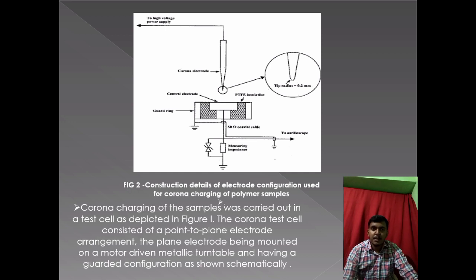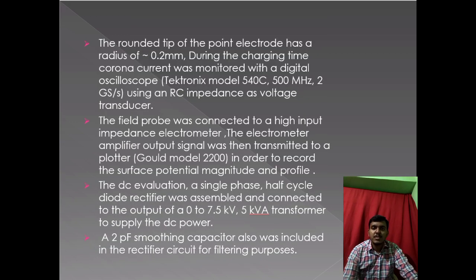After corona charging, the samples were exposed to the sensing head of the probe by rotating the grounded turntable. The field probe was connected to a high input impedance electrometer, and this output signal was then transmitted to the plotter in order to record the surface potential magnitude and its profile. For charge decay measurements under high humidity conditions, fog was generated with an electric heater and kept in the test cell at the end of corona charging.